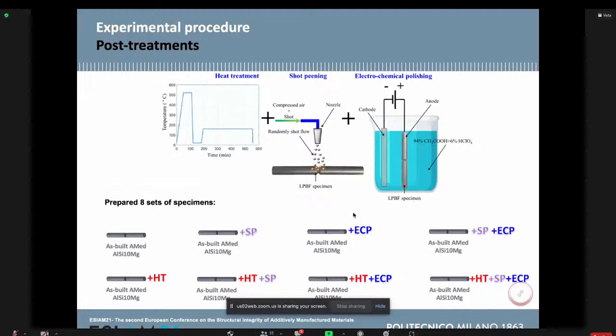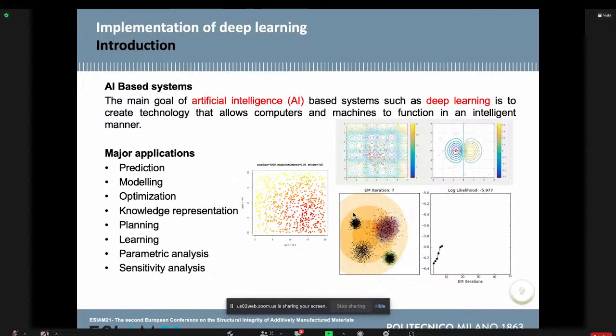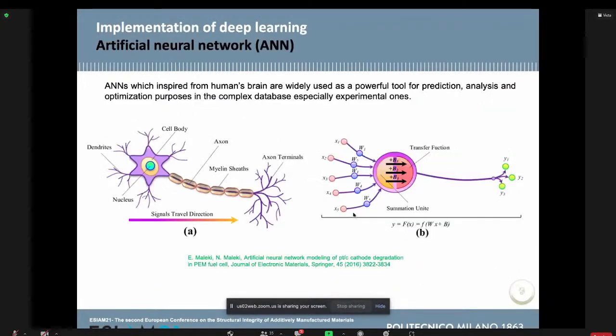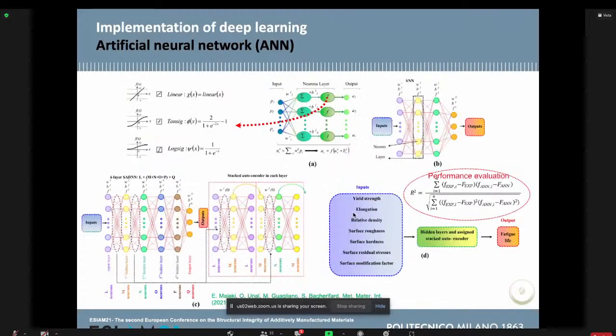With a combination of all of these treatments, we got 8 different series of specimens. Then we used artificial intelligence to model the process. We considered yield strength, elongation, density, surface roughness, surface hardness, surface residual stresses, and surface modification factor as inputs, and we considered the fatigue life as the output of the process. We used the correlation coefficient R2 for performance evaluation.